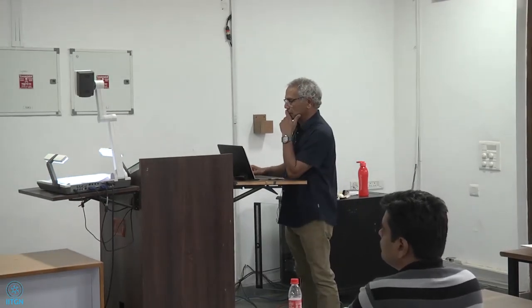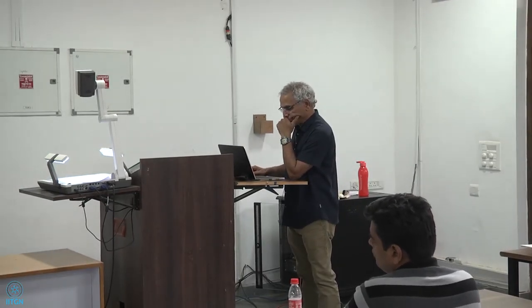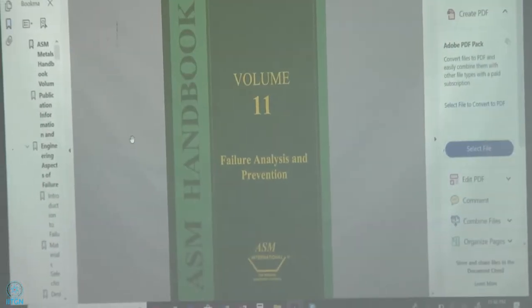Okay, let me just put this up again here. So this is from that paper, from the Royal Society paper. They call it the rogue grain combination. There is a loading direction, soft grain, hard grain, soft grain again. So it's all about transfer of slip and fracture, where it's taking place in those grains, essentially. Okay. But my thinking is that anytime you have a hard time transferring slip, you're going to get a fracture.